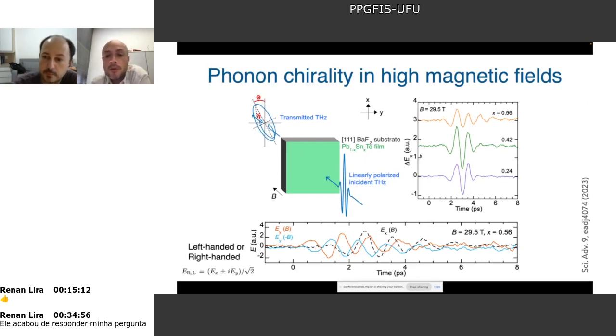Okay, so this axis is called X. The light is transmitted here through X, and along X, I can see that there is a very large change in all the samples for very high field, here almost 30 Tesla. So they all have a change due to the application of the magnetic field. However, it's more important to note what happened in the perpendicular direction. Here we call Y. So there is a new component. Here there appears EY, here in orange.